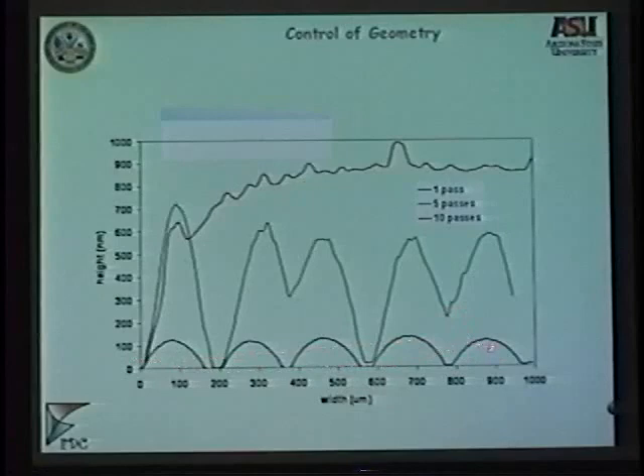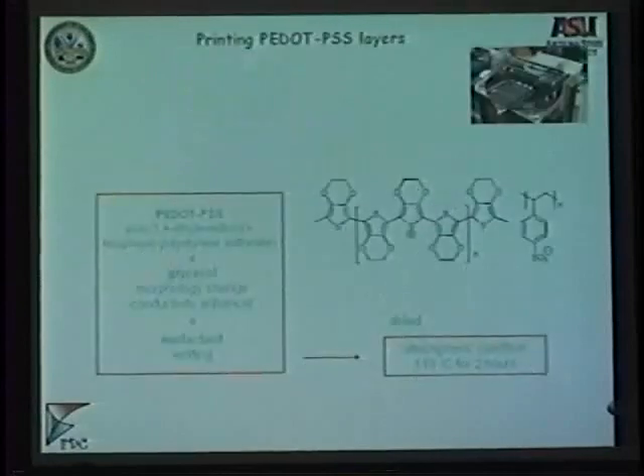This would be an application that we are working on under California support, where we increase the light into the solar cell. That way we increase the absorption and thus the efficiency. For OLEDs, this same structure could be put on the other side of the substrate and extract the light out of the substrate. So here we're making the deposition by inkjet. You could still deposit, and by controlling the ink chemistry you could basically form a layer. And this again can be controlled by controlling the surface tension of the ink that you're printing.